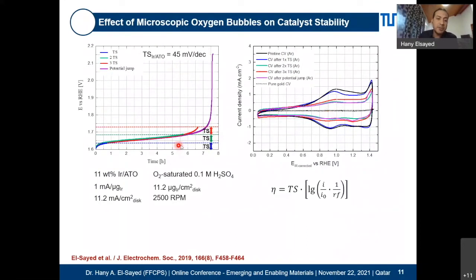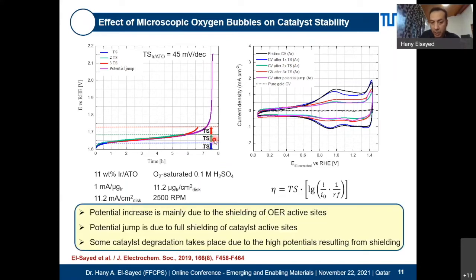So this is the jump that is basically called in literature complete collapse of the catalyst. And in this case, of course, we still have the catalyst there, or at least we have about 40-45% of the catalyst there. So that's why we really believe that what is happening is just blocking of the catalyst layer by oxygen bubbles. That's what we conclude. So at least, not everything, but we think it's significantly contributing.